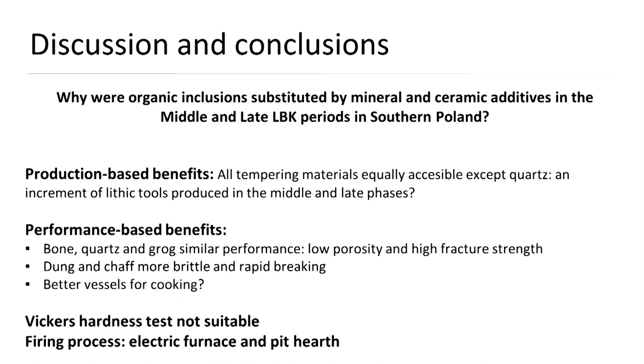Considering the results, we can hypothesize whether they had more resistant vessels in the last period of LBK, while they would have been more brittle in the early phase. Another interesting result is that it was possible to dismiss the Vickers hardness test to examine the effect of temper on clay and to apply in specimens fired in a hearth.